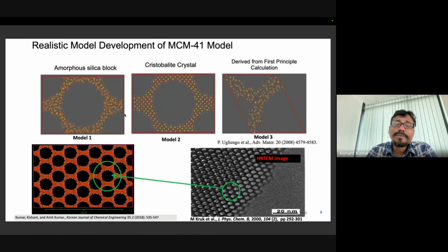That's one material called MCM41, which is a class of silica material, called silica mesoporous material. Basically the pore size of this material is between 20 to 30 angstrom. So it's greater than microporous material, so it comes under the mesoporous scale. So it's called mesoporous material. So you can see this image over here.